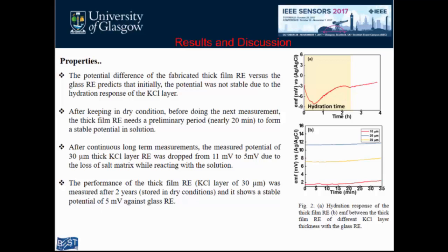And here is another test I did, with the thickness of this KCl salt matrix in different layer thicknesses, to check the performance. And I found that the lower thickness stabilizes easily, but the higher thickness has a long lifetime also.